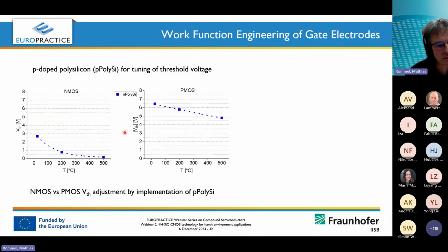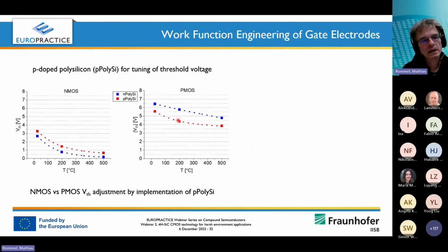And also the difference between the NMOS threshold voltages and the PMOS threshold voltages is relatively big, which is due to the material and some other issues. I will not go into detail in this presentation here. But for example, if we use highly p-doped polysilicon, we can get threshold voltages which are closer to each other. And that's something which is, of course, wanted in principle. And we are still working on this to improve this further.